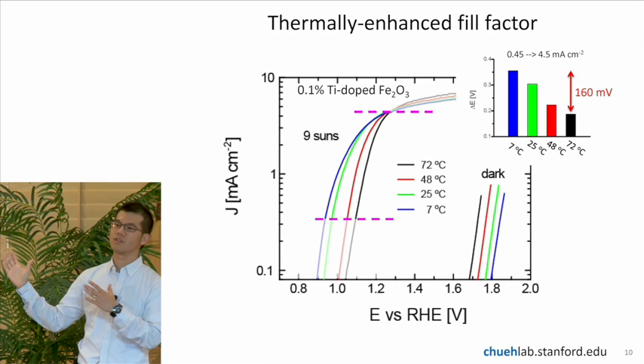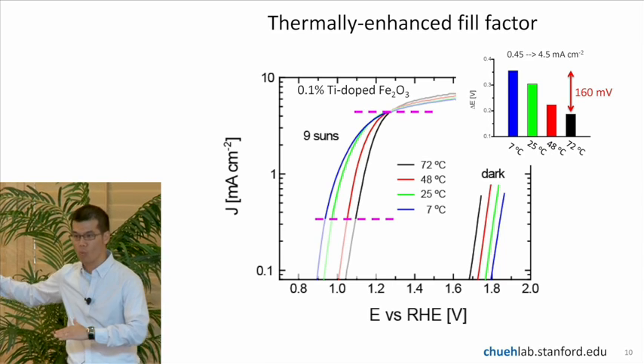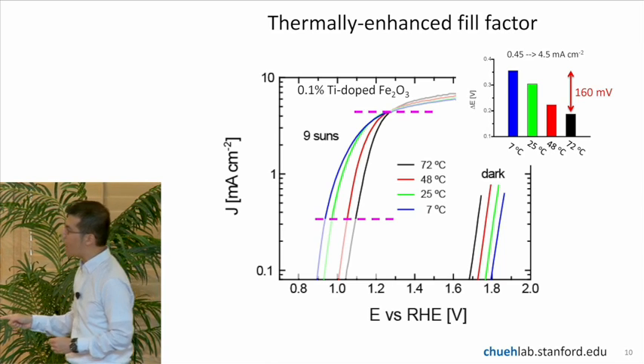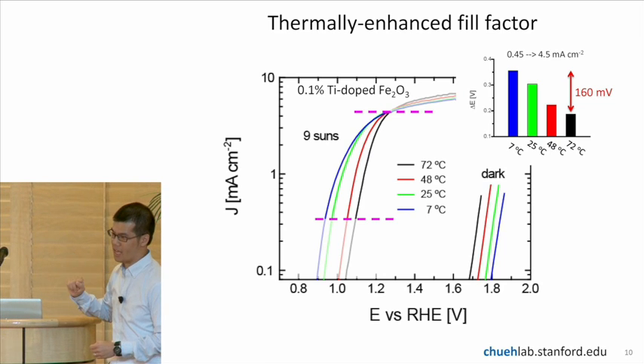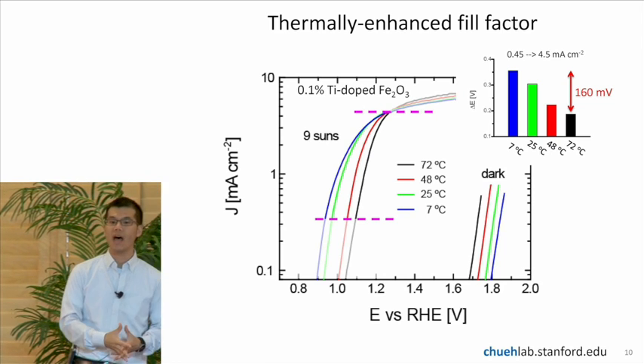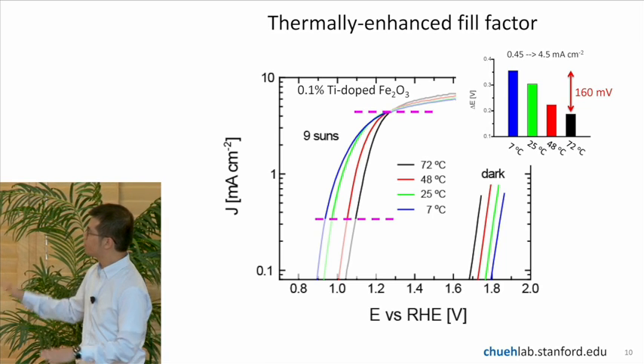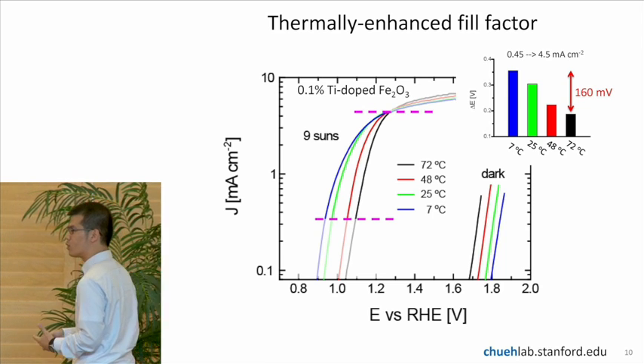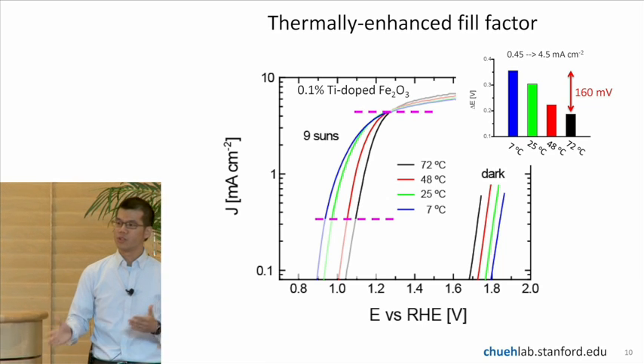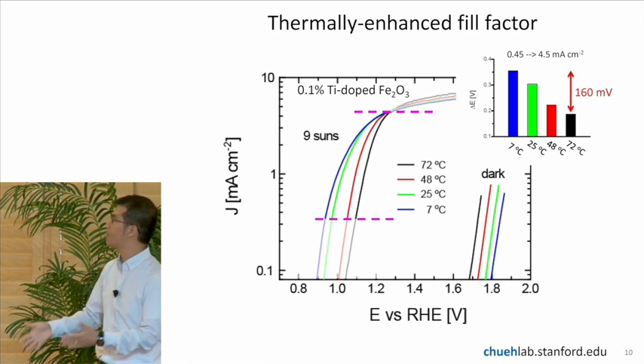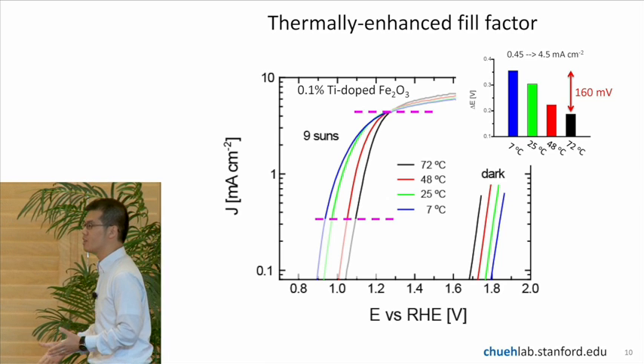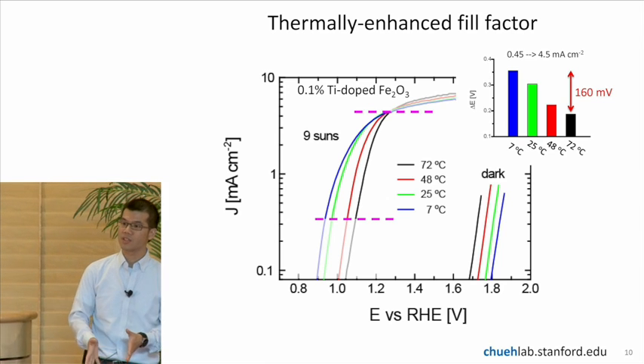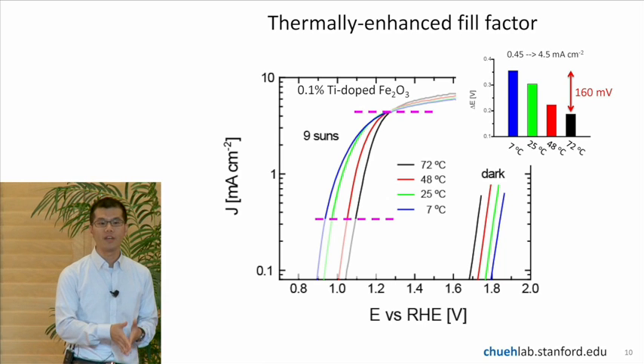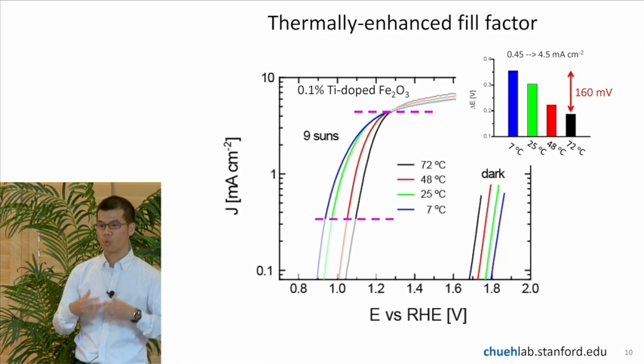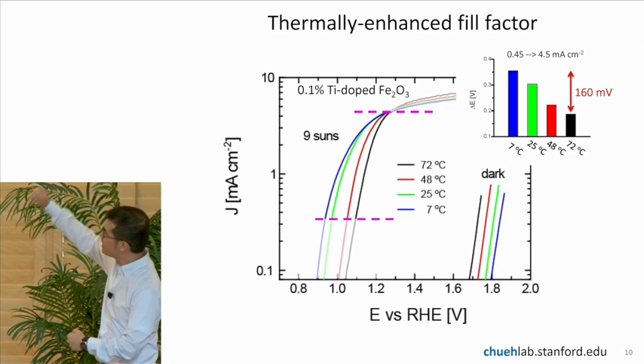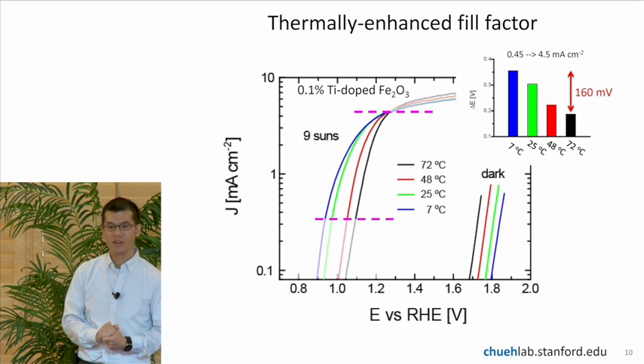So in the previous slide, I showed you how the onset potential, so when the current starts to take off. This plot is showing you how high current behaves. And this is actually where it matters because we will not want to operate our cell at very low current. So this tells you by increasing the fill factor with thermal activation, you're able to achieve higher current with less applied potential. And the reason for this, we have shown, is due to the much improved mobility of the minority carrier in iron oxide. So we're better able to separate the charge, and that's leading to a much faster rise of the current with voltage.